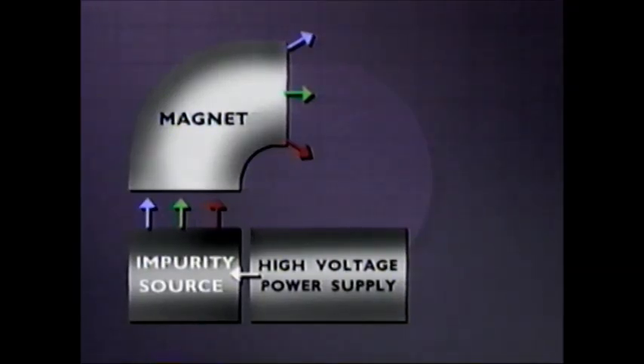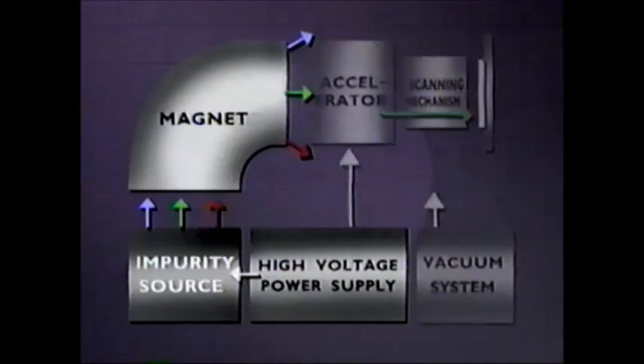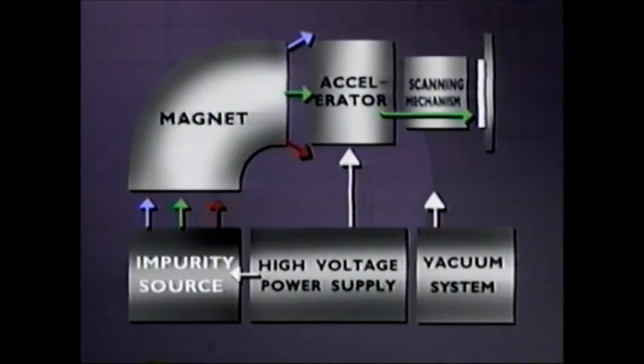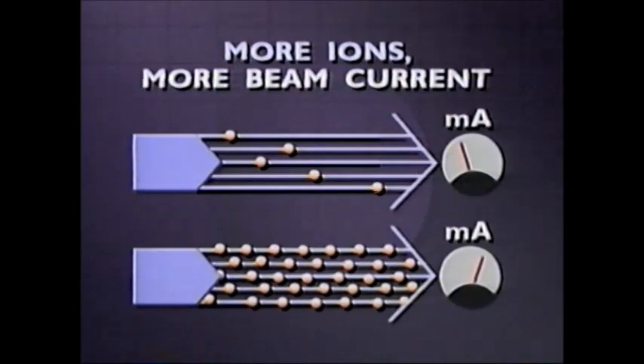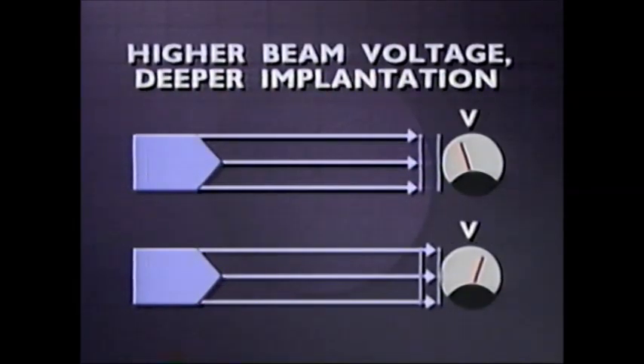Depending on the charge of the particles passing through the magnetic field, different species of ions will be separated from the beam by changing the angle of the exit trajectory. The desired ions are focused by the beam scanner and onto the wafer. The accelerated ion beam is electronically scanned over the surface of the wafer. The more ions in the beam, the higher the beam current and the more dopants the beam will deposit in a given time. The higher the beam voltage, the deeper the ions will be implanted in the wafer.